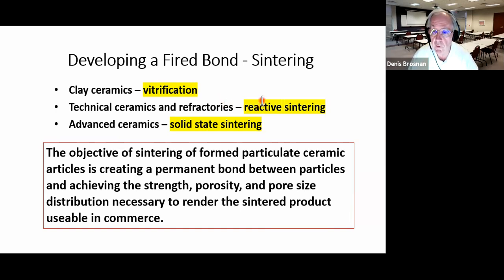So once the ceramic is cooled off, a major part of the bond between the particles are new mineral structures that are formed in the firing process. There may be some glass left as solidified material, but that's reactive sintering. Now, in advanced ceramics or high purity ceramics, solid state sintering takes place. That means that there's very little or no liquid, no transient liquid that's present, and atom movement is by diffusion to points of contact between particles that form the solidified bond, the fired bond in sintering. So the objective of sintering is to achieve that fired bond at particle-to-particle contacts to reduce the porosity that's present in the formed ceramic and to give it its strength.